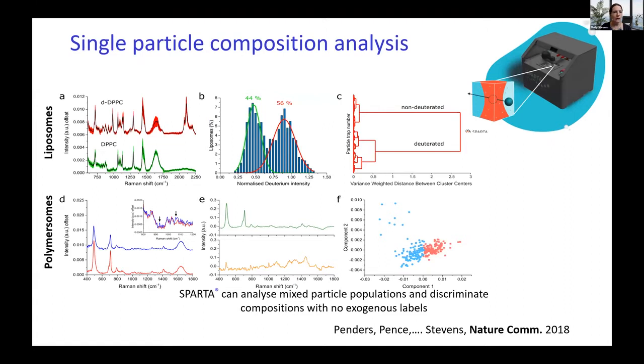So here on the top row, we have two different types of liposomes, some deuterated ones and some non-deuterated. And you can look at a mixed population of these with the SPARTA, and without having to label them or anything, you can pull out differences in their chemistry. And then at the bottom, we have two different types of polymersomes made from polymer chains that are rather similar, except the blue one also incorporates a heparin group. And again, without having to label these, you can measure that mixed population and distinguish between those two different kinds of particles.